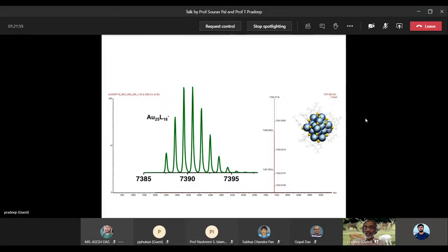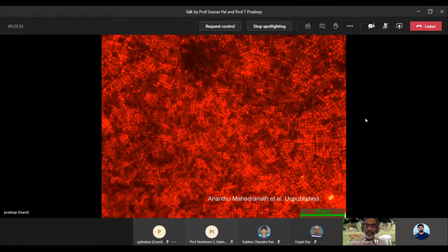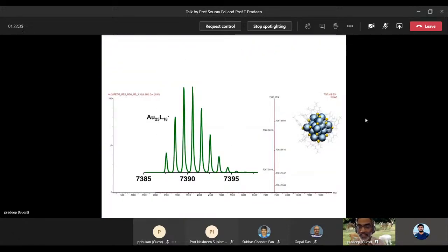Today we have a mass spectrometric technique, an extremely soft ionization technique, electrospray ionization. If you do electrospray ionization reasonably well, this particular one is nano ESI, you get this spectrum. And you note that there is nothing here, which means that this ionization is super soft. It doesn't impart energy into the ion to cause fragmentation. Let me go back and show you this spectrum once again. And this is a high resolution mass spectrum.